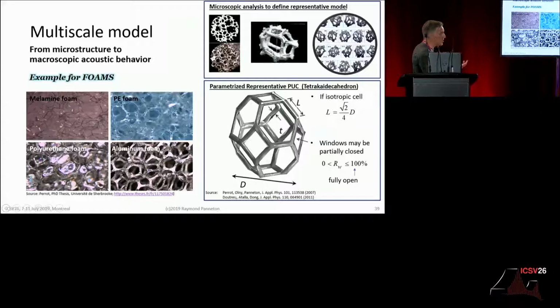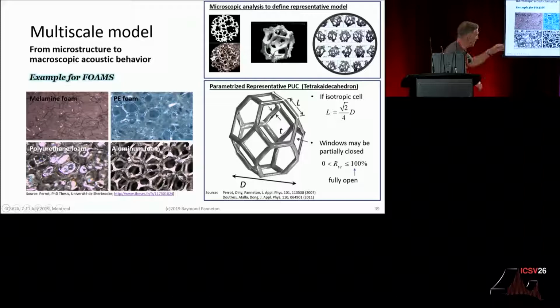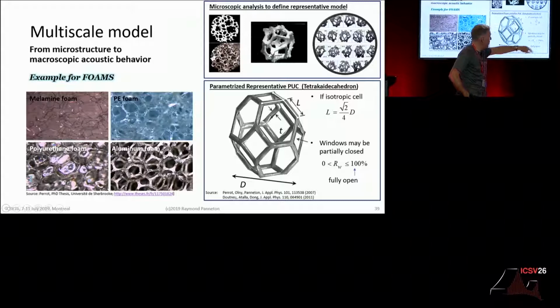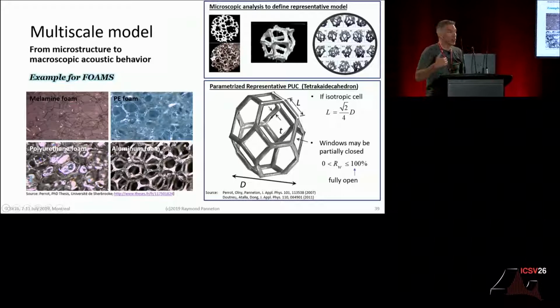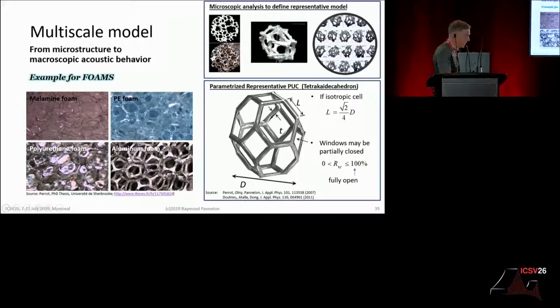we can also add another parameter from Olivier Doutres and Atalla's works, which is the opening ratio of the cell. So if it is fully open, like this one here, so all the windows are open, then we have an opening ratio of 100%. If it is zero, it would be all closed cells, but it is not good for acoustic purposes because the acoustical wave cannot go through the material to dissipate, as I mentioned before. So this is the model for a foam, a cellular material.